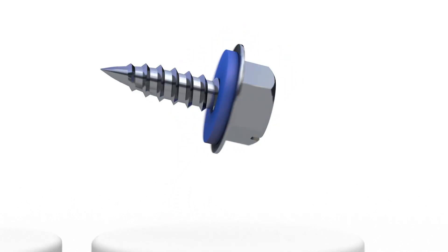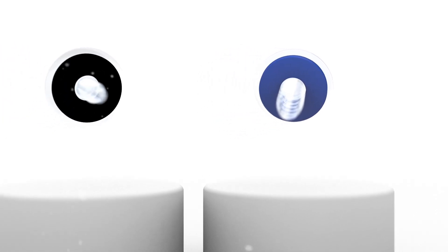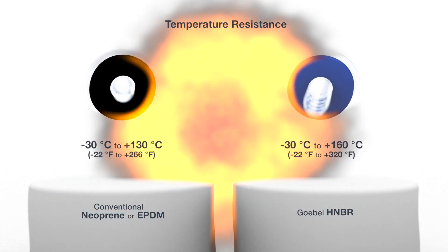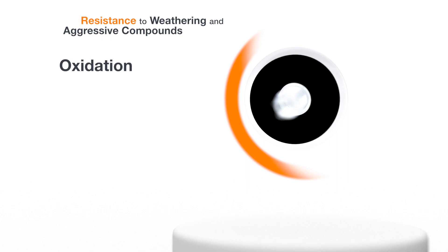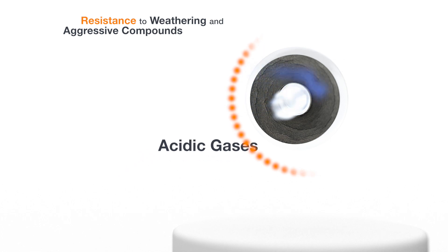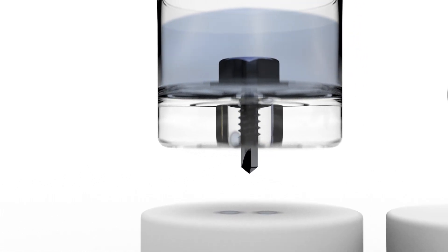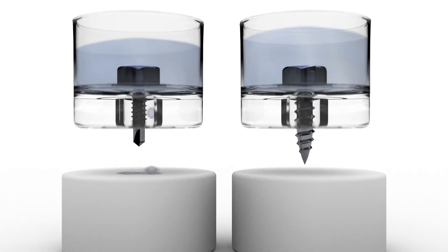The technical difference of the newly developed blue HNBR duplex sealing washer proves itself in a considerably higher temperature resistance of about minus 30 degrees to plus 160 degrees Celsius. Also in comparison, the higher weathering resistance versus neoprene and EPDM, as well as the resistance to mineral oils, ozone, seawater, and acidic gases, prevents early breaking of the sealing washer. This means the penetration of water is almost impossible and the insulation is not damaged. Therefore, the CUI problem is minimized most effectively.